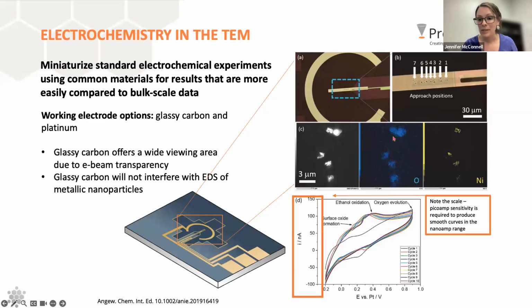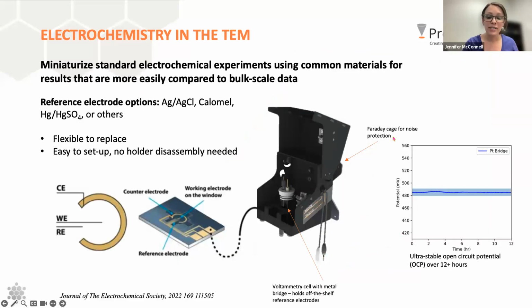The counter electrode is always platinum. And then for the reference electrode, you have the option to use the platinum. It's patterned as platinum on the chip. You can use the platinum as a pseudo reference electrode, which a lot of our customers have done in the past. But we've recently added the option to use a more standard reference electrode, something like silver chloride, saturated calomel, mercury sulfate, whatever might make the most sense for your experiment. We've designed a means of doing it where you can incorporate your reference electrode. It sits outside the holder, but you purchase them off the shelf from somewhere. So if you need to replace the silver chloride with something else, you're not buying something specialized or custom to fit in here. It's off the shelf from standard companies that sell those.